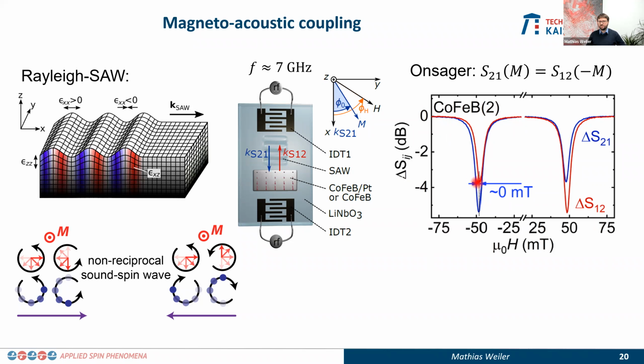So if we switch the direction of propagation of the sound wave, sorry, we go from the red curve to the blue curve. That corresponds to an acoustic wave like that or an acoustic wave like that. And you can see that the transmission is definitely different at this location. It's the same out here, where we are at a point where there's no interaction between the acoustic wave and the spin wave. Okay? But here where there is an interaction, it becomes non-reciprocal. Same over here. And then the Onsager relations dictate that this blue curve over here, at positive field, is the same as the red at negative field, and vice versa. Okay? And that's what we observe.